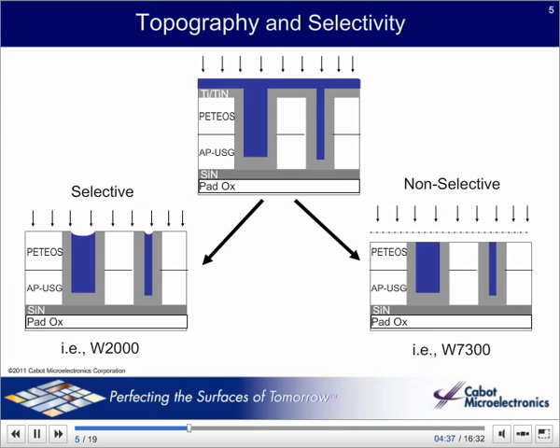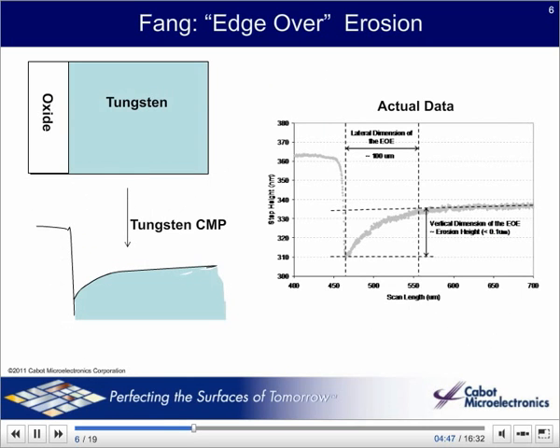As is often the case, chip designers and CMP engineers need to work together to make sure that the design and manufacturing process tolerances match. A special type of erosion is pronounced at the interface between two very different materials at the very ends of an array. It is believed to be a function of differences in coefficient of friction and grain structures as the two distinct materials come together. The net effect is a deep fang that occurs between the two materials. This is a fairly common failure mode for CMP and often requires fine tuning to reduce the fang to acceptable levels.